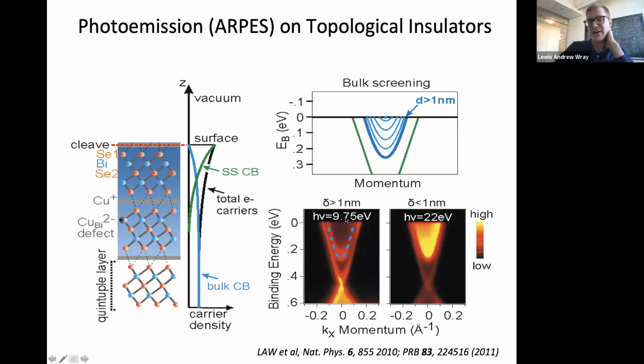If we use a very low photon energy or an extremely high one, we can see the bulk states pretty well. This is a measurement like that, where you see these are bulk states. They look like a parabola, because we're used to thinking of, for a massive particle, energy being proportional to momentum squared, as p squared over 2m. So energy on this axis, momentum on this axis, and the states are a parabola. Great. But crossing from the top of the image to the bottom, we have this X that does not look like a parabola.